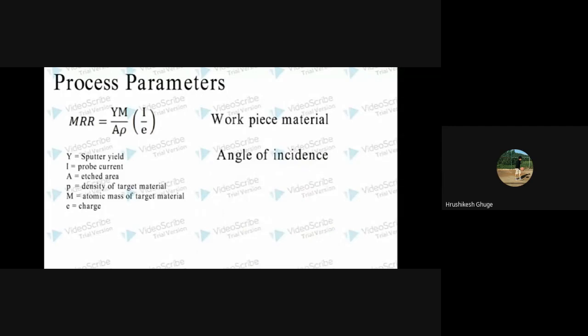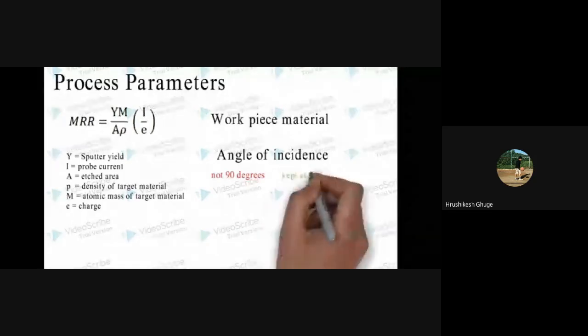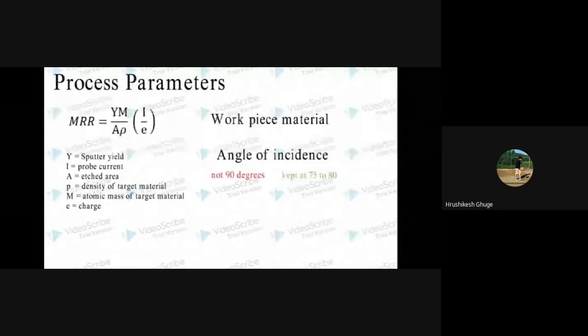Increasing this angle increases the number of ion atom interactions, which results in increase in sputtering rate. But it cannot be kept at 90 degrees because there is a higher probability of collision between the incident ions and the sputtered out ions when it is kept at 90 degrees. Therefore, the range is kept at 75 degrees to 80 degrees at which we can get the maximum sputtering yield.